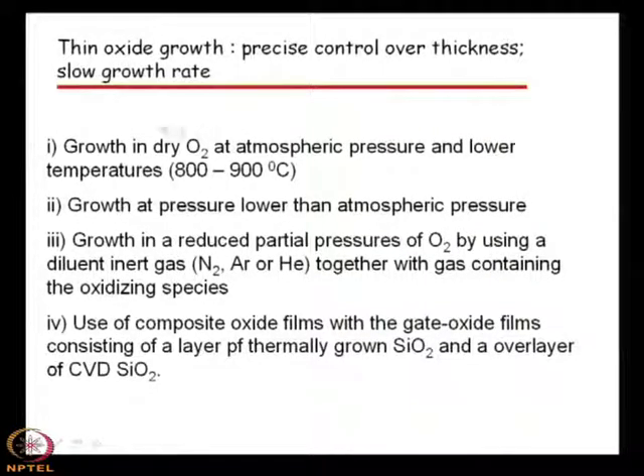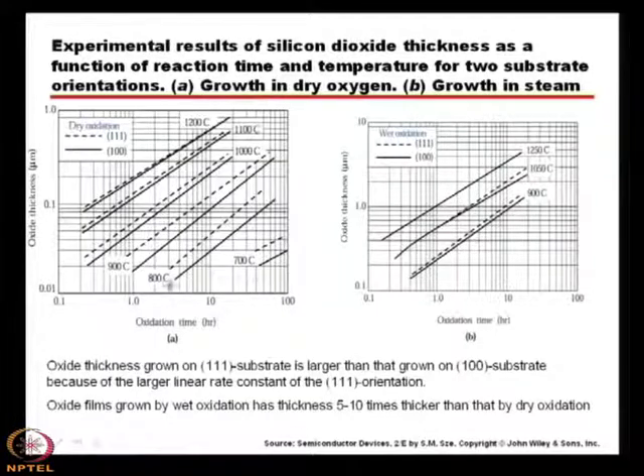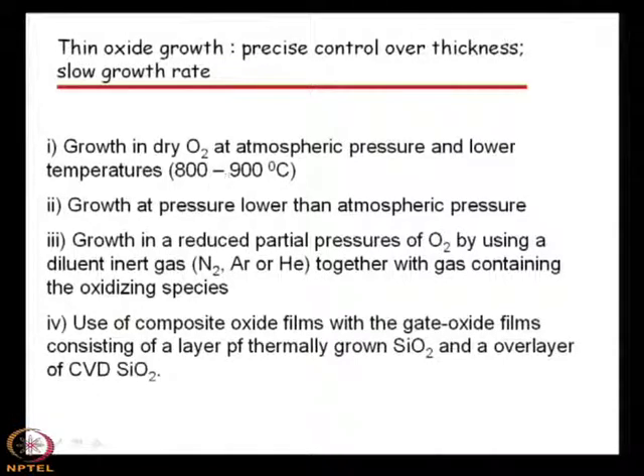Then what are the processes, what are the major steps that the industry has taken? So, the formalities are: one is growth in dry oxygen at atmospheric pressure and lower temperatures. Lower temperatures means 800-900 degree centigrade. So, here you see that it is 800-900 degree centigrade, atmospheric pressure and low temperature. This is dry. Another protocol can be growth at pressure lower than atmospheric pressure.